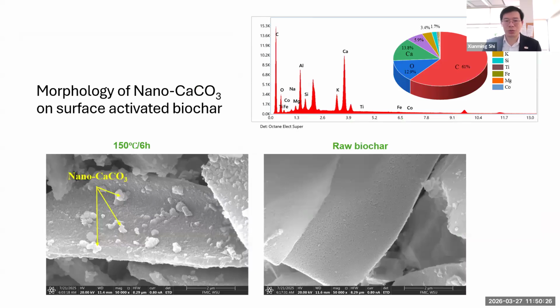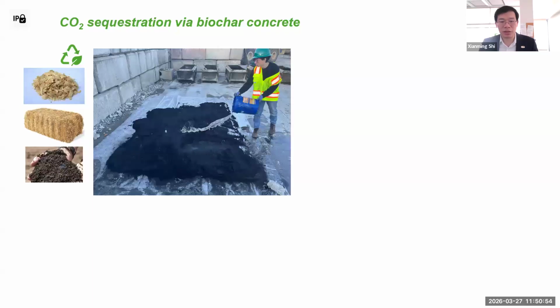Just to share with you a picture of nanocarbonate. Since we talk about nanocarbonate, here's the direct evidence. You actually see them, right? On the right-hand side, the SEM, or scanning electron microscope, image shows the raw biochar pretty smooth, but after carbonation, you see the nanocarbonate. But the challenge is that in the field, we probably don't have this kind of ability to control it. So we did something really rough, as you can see here. It's a very simple 2 cycles of wet-dry under ambient temperature with the concrete washout water. That's how we did it.